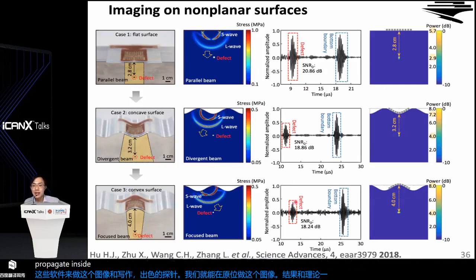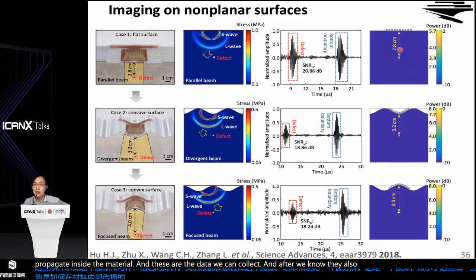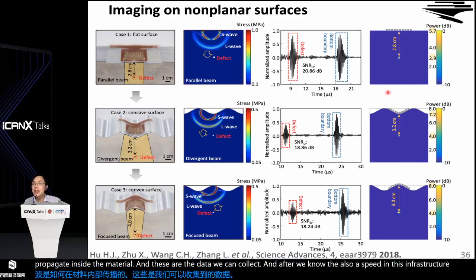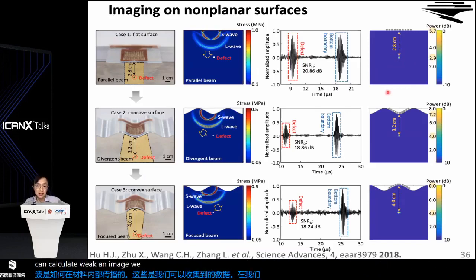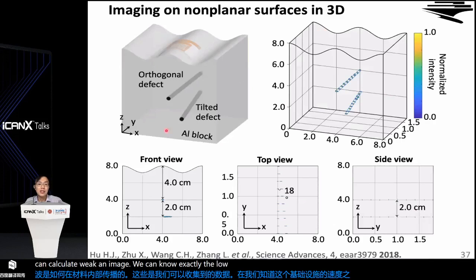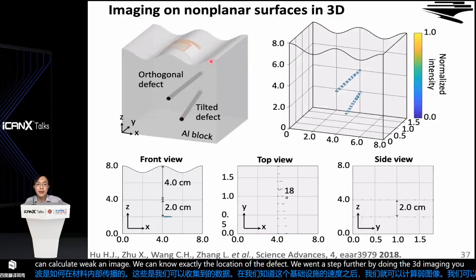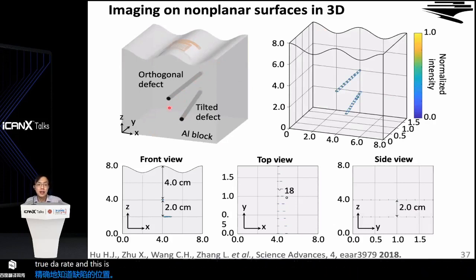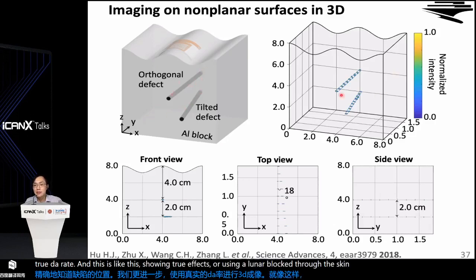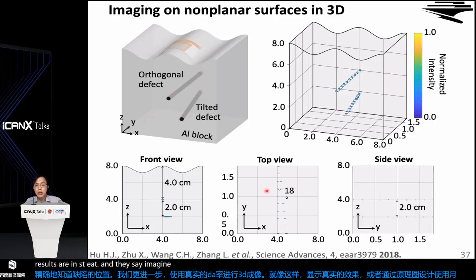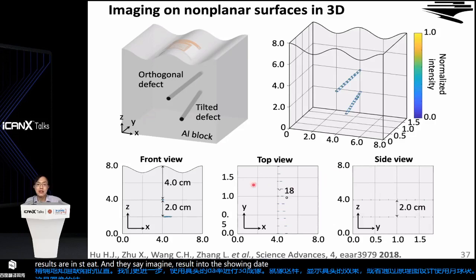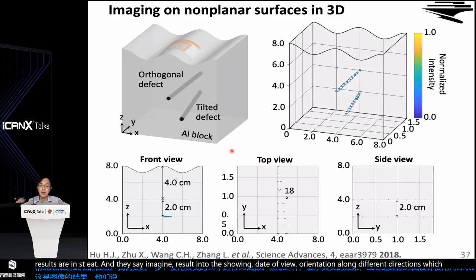And this is a simulation showing how the ultrasonic wave propagates inside this material. And these are the data we can collect. After we know the ultrasonic speed in this infrastructure, then we can calculate and image, and know exactly the location of the defect. We went a step further by doing 3D imaging using a 2D array. This shows two defects within an aluminum block. This is the schematic design, this is the imaging result in 3D, and this is the imaging result in 2D, showing the view orientation along different directions, which match this design perfectly.